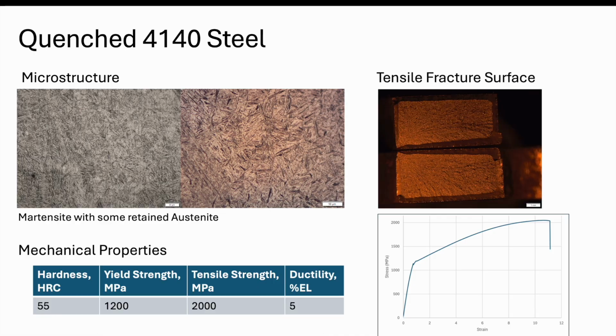That brings us to the last part that I want to show, which is when we do the tensile test, we look at the fracture surfaces and we can draw some conclusions from that as well. Here are the two fracture surfaces that we see. In the middle part, it's relatively flat. You actually see some river marks, from the fracture propagating in the center of the region. Then you see a region around the edge. In this case, we have a rectangular cross section. The region around the edge has an angle sometimes of about 45 degrees, but this top surface here is flat. So the middle is the brittle region, and the edge is the ductile region.